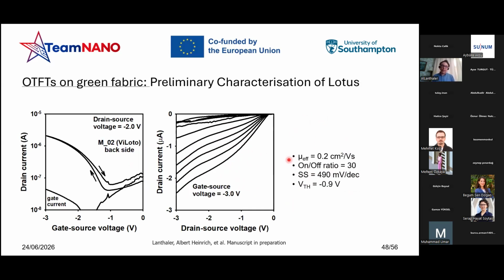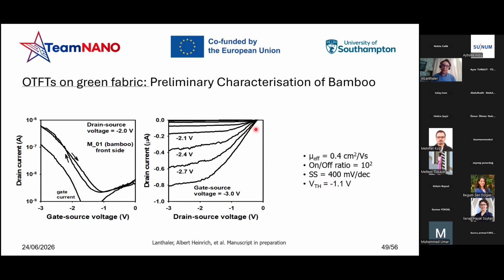Coming to the lotus one, as you can see here, the linear output curve is much more highlighted, with no saturation visible at all, which is also justified by the subthreshold swing being very high compared to the others, 490 millivolt per decade. The gate current, I would like to highlight, is still in the same range as before. Last but not least, the bamboo one was the best compared to the others, achieving a higher mobility, 0.4, a higher on-off ratio, and a proper saturation area with a subthreshold swing of 400 millivolt per decade.